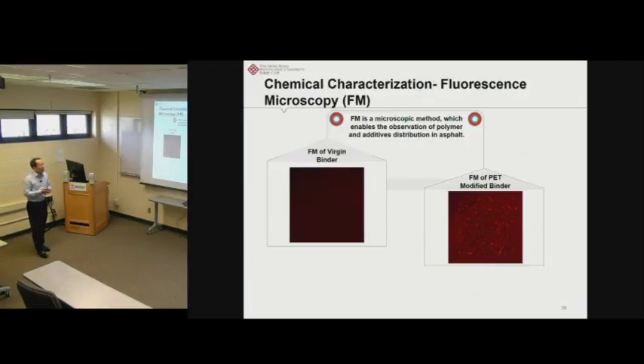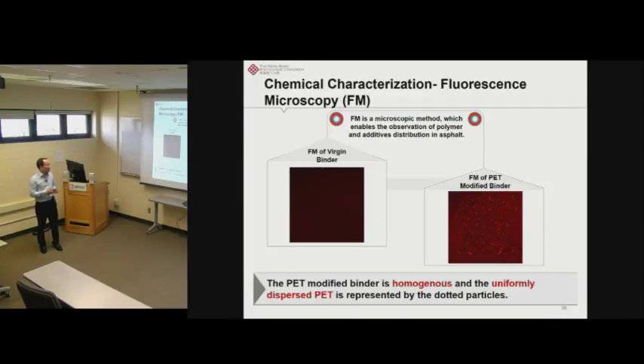Following all these rheological property tests, we also did some chemical analysis. Here you can see some results from the fluorescence microscope test. The one on your left hand side is for the virgin binder, and this one is for the PET additive modified binder. From this image, we can see those red dots, which are relatively uniformly distributed. This indicates our PET additive has a relatively uniform and homogeneous distribution inside the binder. This is important to ensure our binder has a consistent material property.